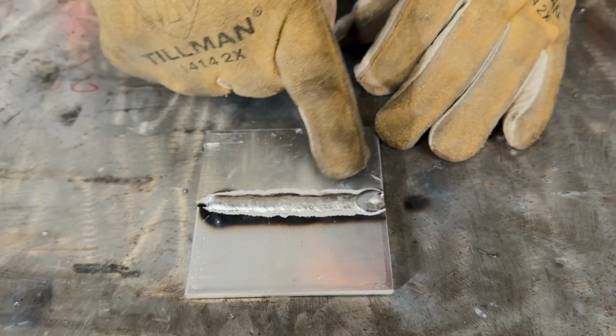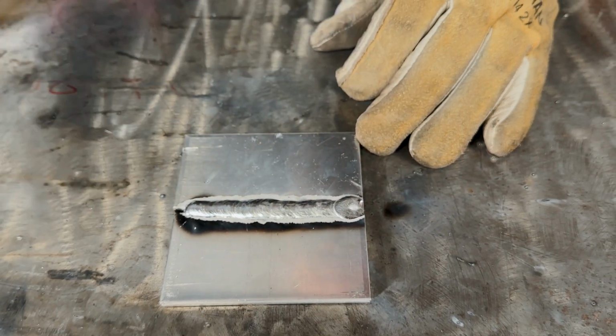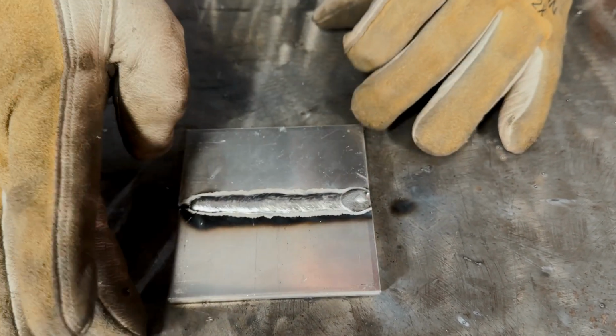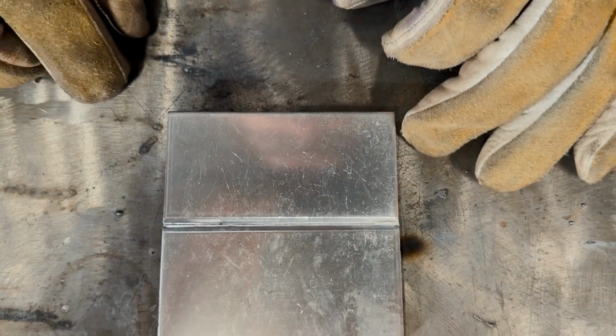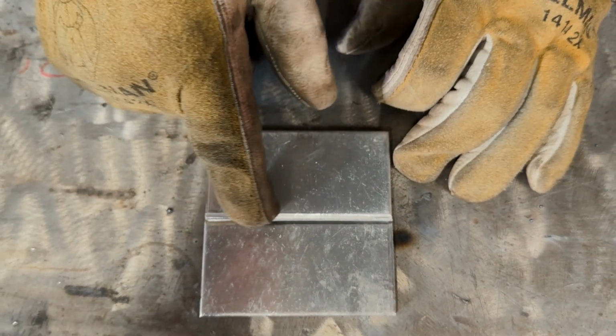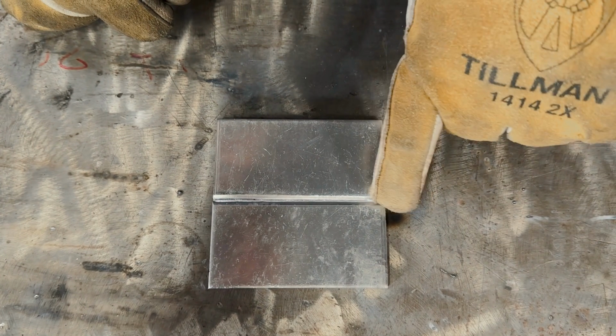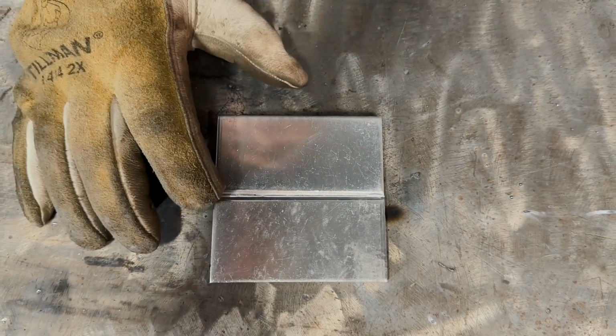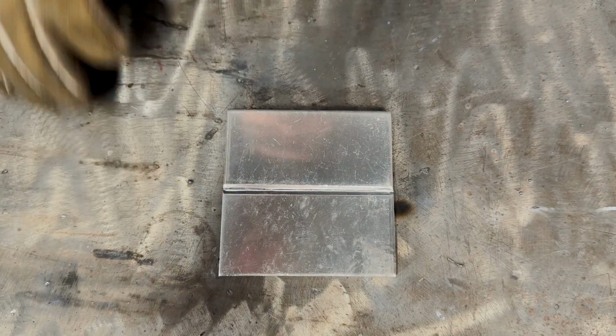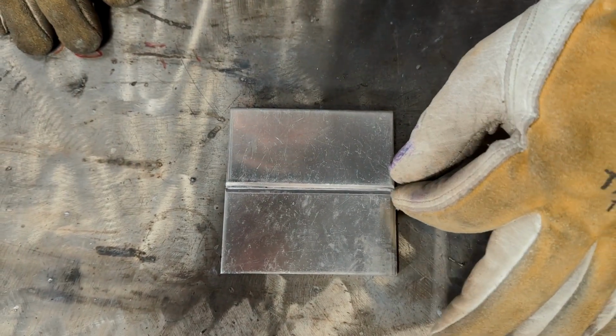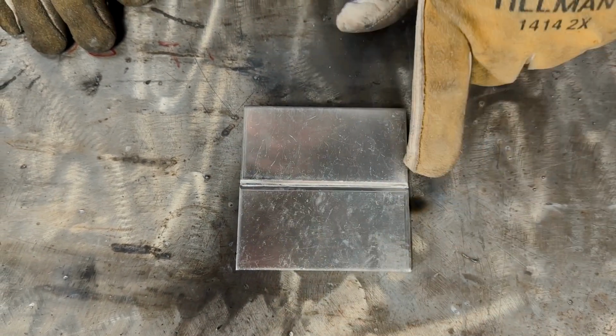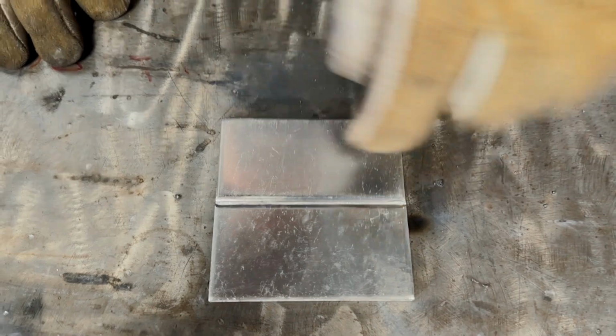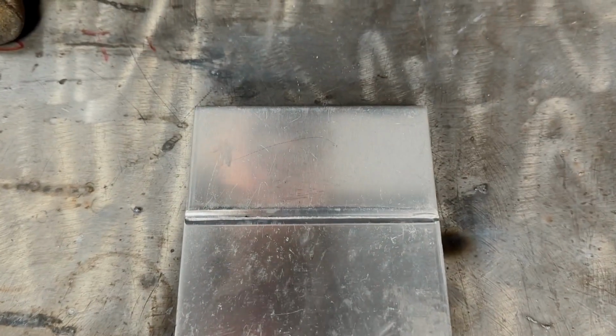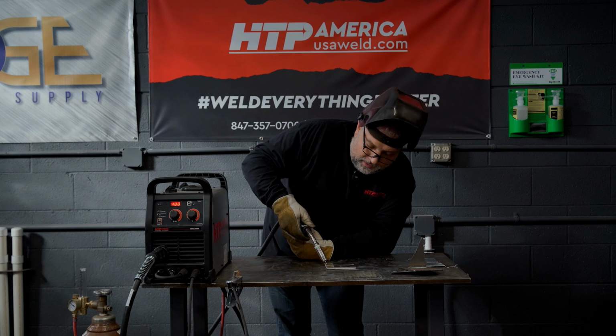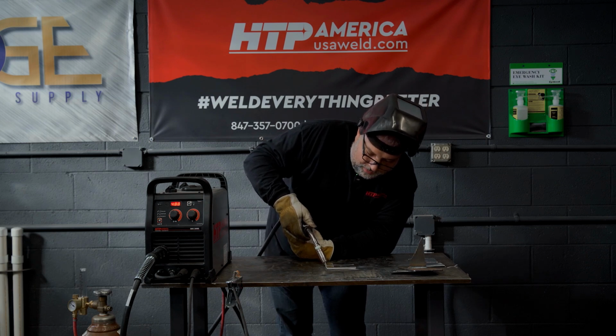Then it heated up really nice, and at the end there's a very minor crater. You could have triggered it a couple more times and filled that crater. And now, moment of truth, backside. You don't really see much at all. It kind of looks like there might be some coming through here, and at the end you see a small deformation there. If you wanted to get 100% weld, if this was a critical item, I'd probably go in with a hard wheel designed for aluminum, grind this out a little bit till I see the other side, the root, and then weld it and fill it in. So now I'm welding the backside here without additional joint prep.